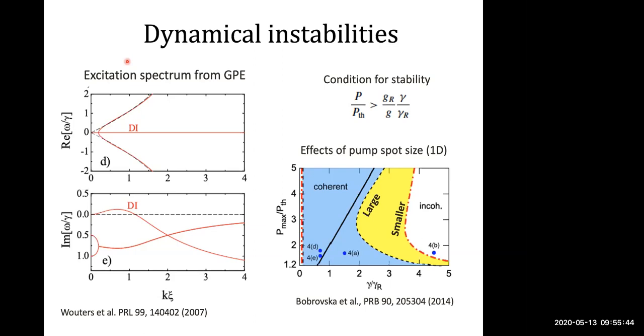If you look at organic polariton lasers under impulsive pumping, you'll find very similar line width narrowing. Now, many organic lasers are studied using nanosecond pulses. And there you can see very narrow line widths above threshold because you're limited by the actual coherence time of the emission burst.